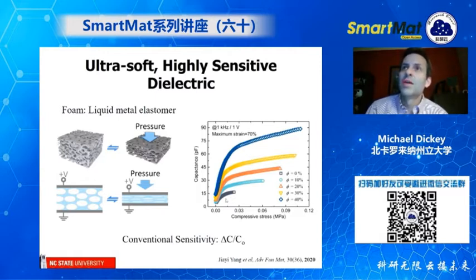And as you can see, this is 0% liquid metal. This is just silicone foam. And if you add more liquid metal, you can actually greatly increase the capacitance. So this makes your device more sensitive. And so there's a measure of sensitivity, which is change in capacitance divided by initial capacitance.